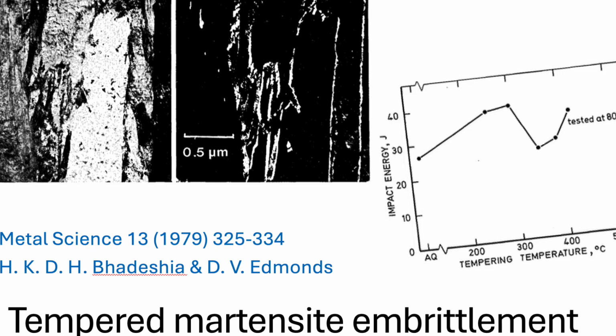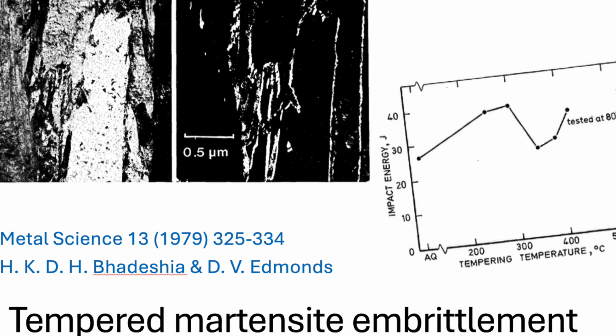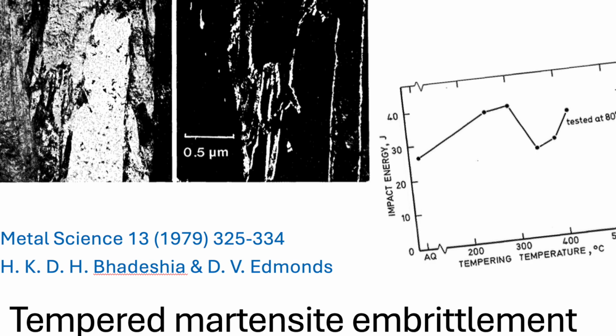Okay, how did hardness behave? Hardness showed a steady, continuous decrease as the tempering temperature went up, from the as quenched state right up to 500 degrees C. Just getting progressively softer? Yeah, just general softening, which is exactly what you'd expect during tempering. So this is a really critical distinction then. The generalized overall behavior, the softening, happens across the whole temperature range. Right. But the catastrophic failure, the drop in toughness, only happens in that narrow, 300-degree window.